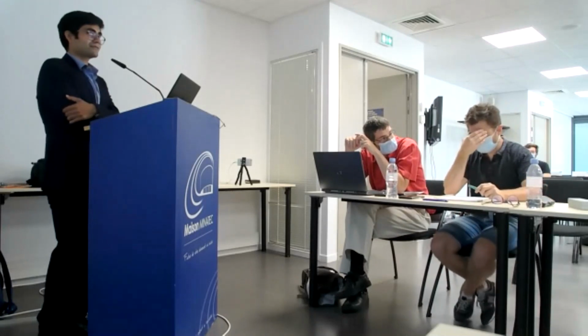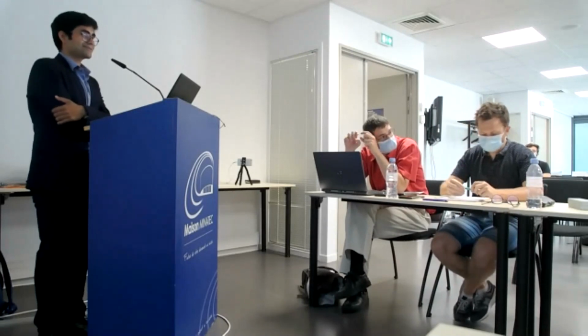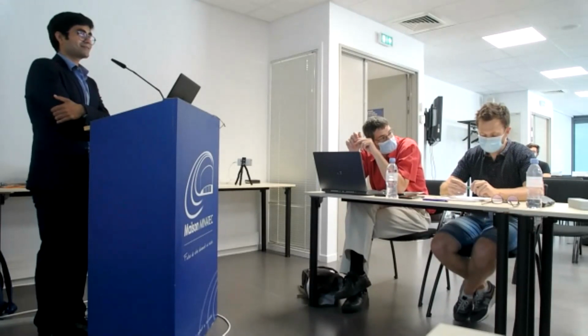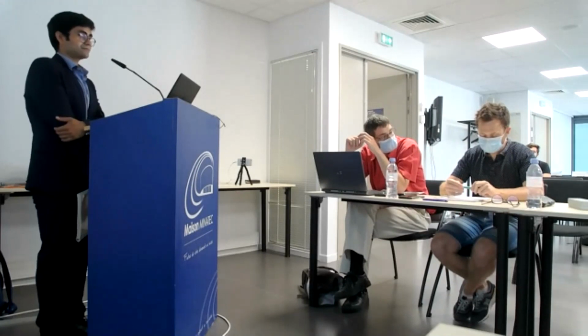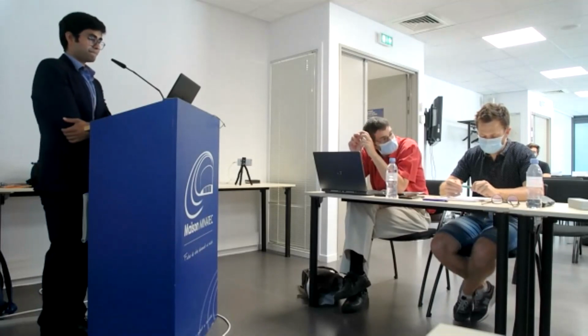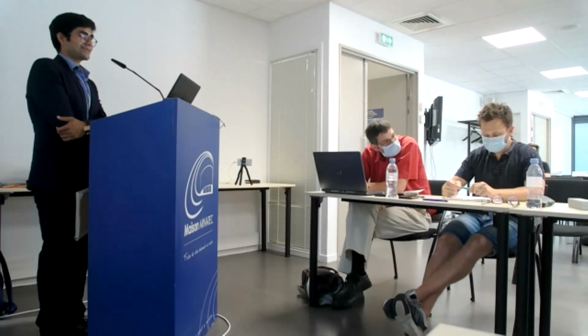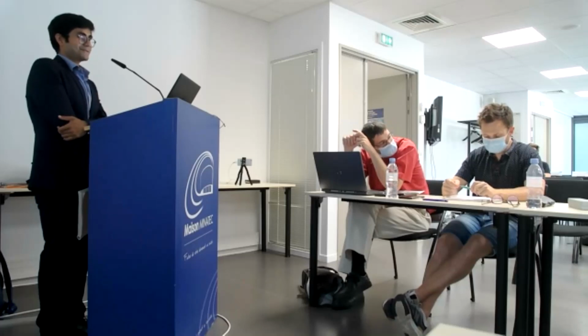First, one of my questions was about this famous pressure drop, but now it's been discussed quite a lot. And effectively, I would say it's probably putting the dust under the carpet, this value. I was wondering, among all the different hypotheses behind this calculation, which ones do you think are the least valid? I will cite three of them. First, also cited by Aude, is the effect of precipitation at the grain boundaries. Your very nice TEM experiments show that you have a very high fraction of precipitation at the grain boundaries. How valid do you think it is to consider the surface energy between two grains when 50% of it is covered by precipitates, which have their own interfacial energy, solid, liquid, and so on? And also, of course, the stress that can be supported by this grain boundary is affected by the precipitation on it. That would be my first comment.